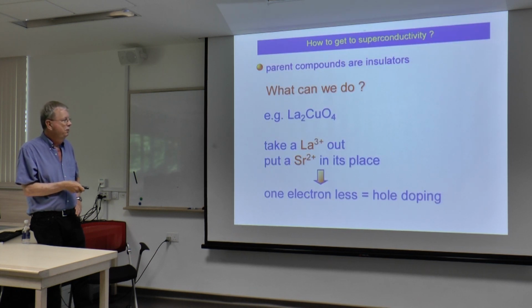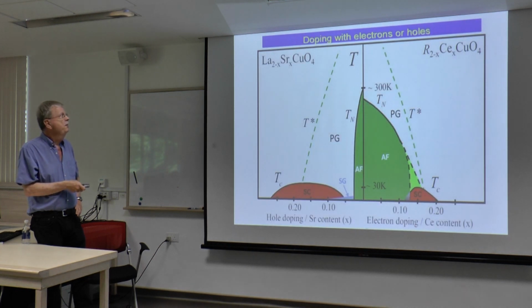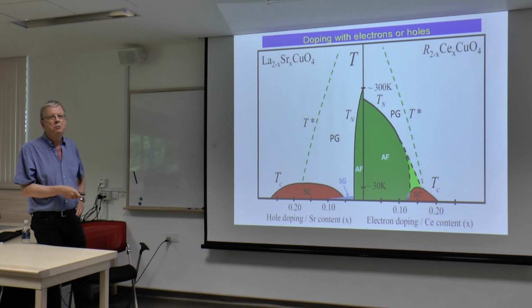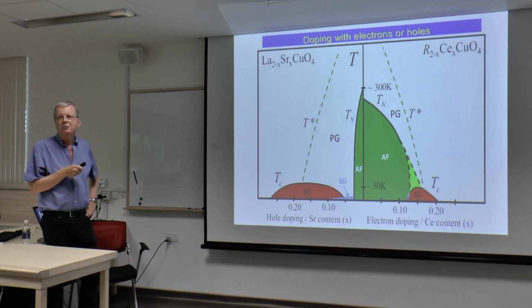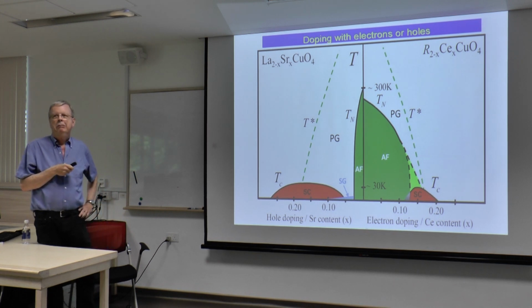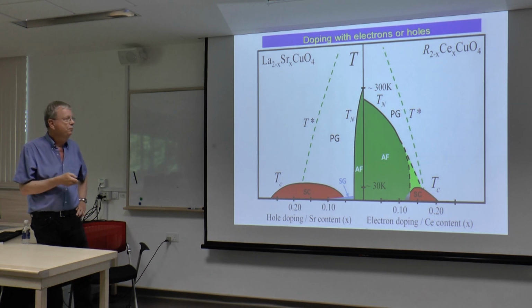Strontium, little hole doping. Here's a phase diagram. So here's hole doping over here. Here's electron doping over here. Here's the superconducting dome. Here's a spin glass, little complication down there. Here's antiferromagnetism. Here's the superconducting dome. Here's a region of coexistence. So people get all excited about coexistent, long-range antiferromagnetism and superconductivity. And here's a region of dispute. I will not enter into this dispute. I have never published a paper in electron-doped 214. Something interesting going on there.